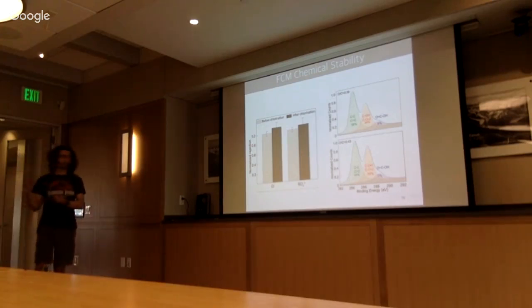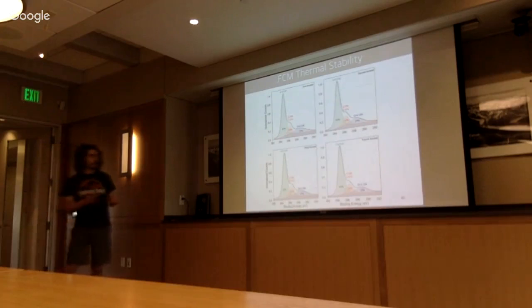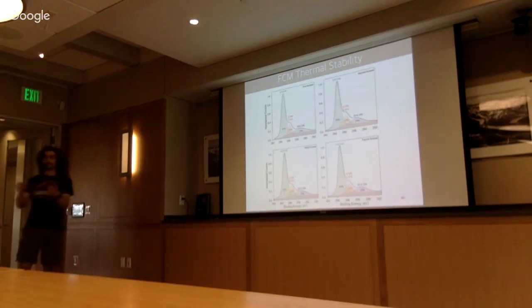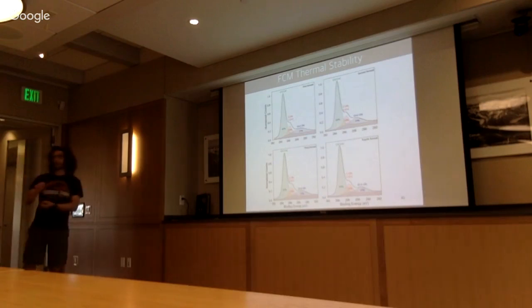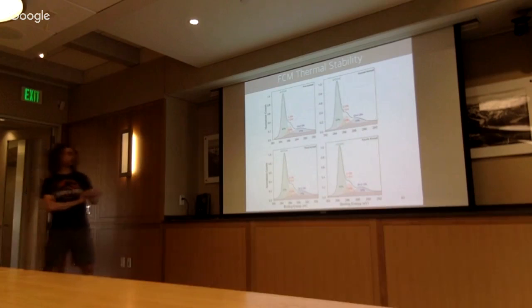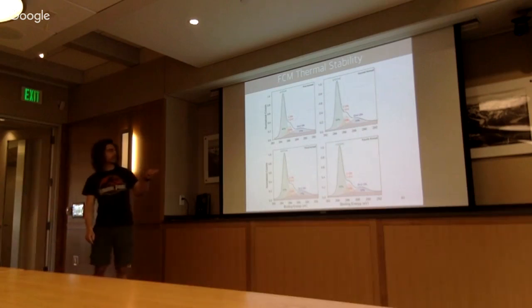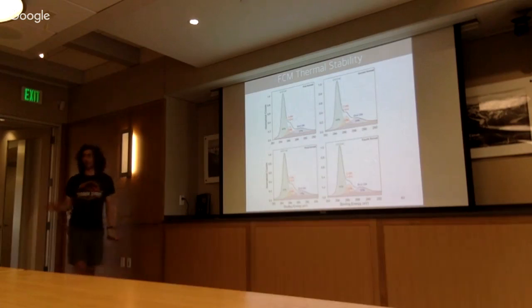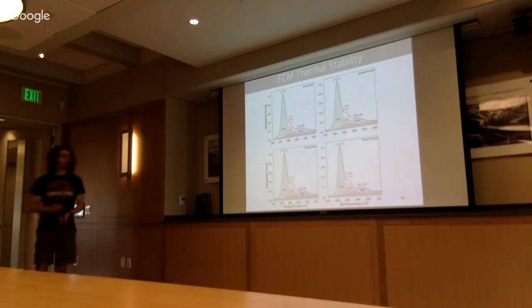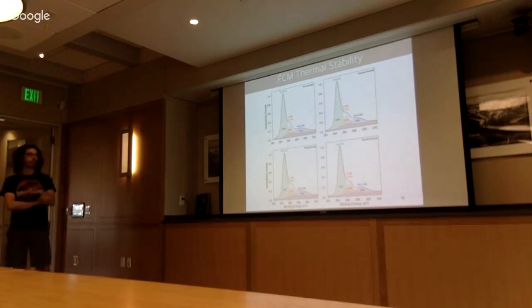Let's see if the membranes are also thermally stable. What we did, we subjected the membranes to annealing cycles. Annealing means you put the membrane in a tube furnace and you ramp up the temperature. Here the temperature is set to 150 degrees. You can see after the first, second, third, and fourth anneal, there's basically no change in the chemistry of the material. So these membranes are resistant to these thermal cycles.